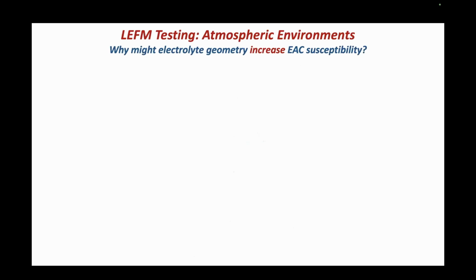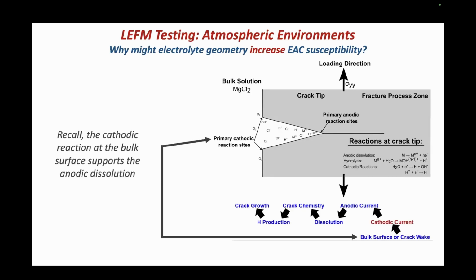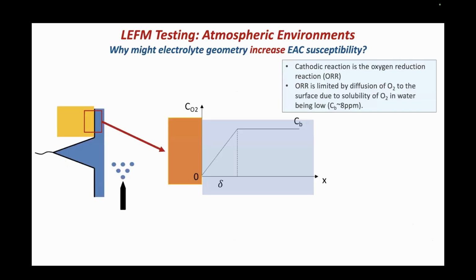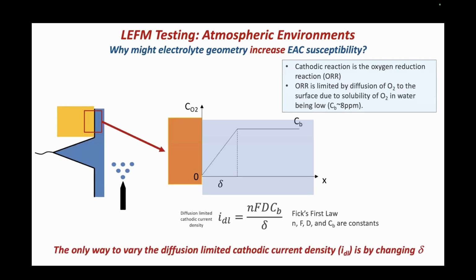within atmospheric environments. Why might the electrolyte geometry increase EAC susceptibility? So recall that the cathodic reaction at that bulk surface is what supports the anodic dissolution. So that cathodic reaction is the ORR, the oxygen reduction reaction, and this is limited by the diffusion of oxygen to the surface, just due to the fact that oxygen is not very soluble in water. And so one of the only ways to change that cathodic current density is going to be by changing that diffusion distance of oxygen and therefore the water layer thickness.